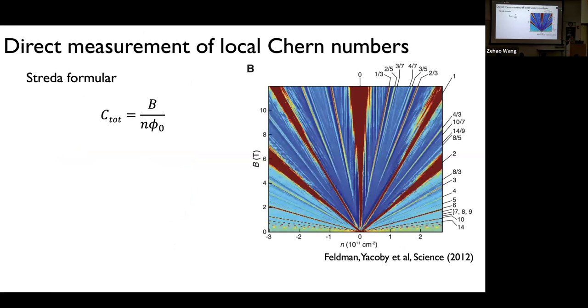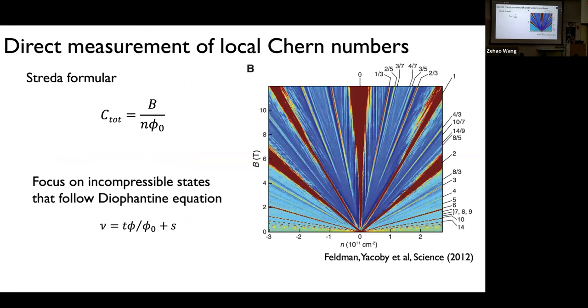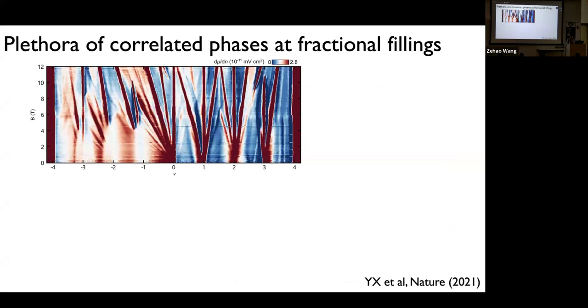This is a characteristic measurement in bilayer graphene that was done, I think, 10 years ago. Then looking at this line, slope, and intercept, you can deduce whether you have a fractional state. And then we applied this to magic angle twisted bilayer graphene. To our very surprise, the very first sample, it just worked.